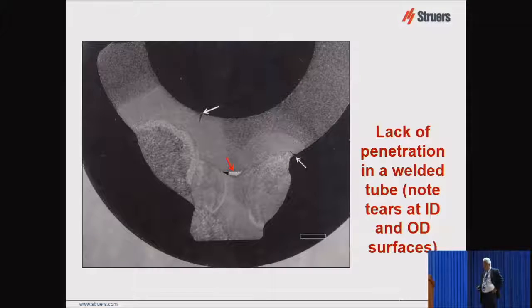And here is a weld in a tube, with a standard macro etch of 10% nitric and water. You can see up here is the base metal, and base metal here. You can see we've got a big weld nugget here. We've got another here, another here, another here. And there's a crack right here at the ID and one at the OD. And of course, those are highly undesirable in a product going into service.